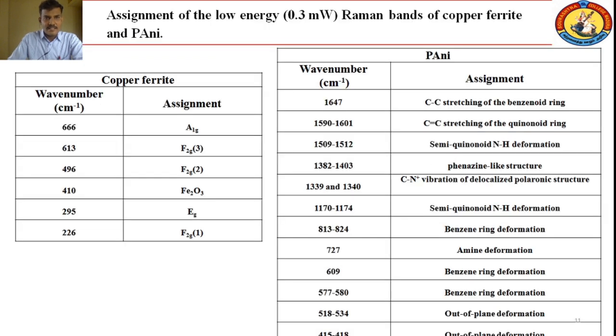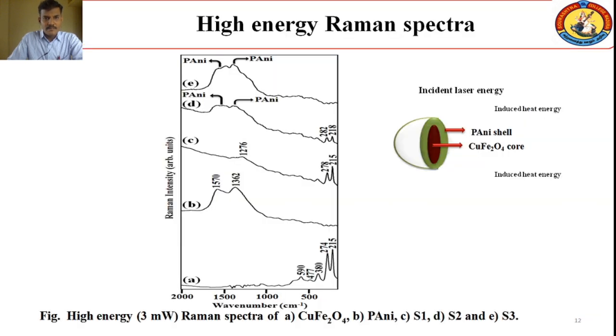Next, this is the characteristic assignment of different peaks that we are getting from the Raman spectra of low energy. Here it's the high energy Raman spectra. Here you can see the same element, but here we are using a 3 milliwatt laser. So when you use the high energy laser beam, the laser beam penetrates the surface of polyaniline. Here you can see a copper ferrite characteristic behavior, and here polyaniline characteristic behavior. In the low concentration of polyaniline in S1, the total polymer chain is destroyed. That is mainly because of the induced thermal energy during this high energy Raman, right?